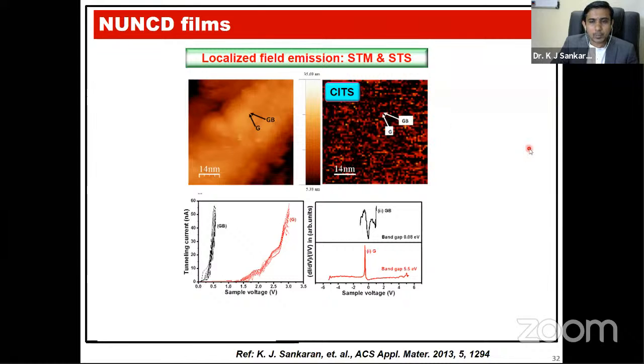So the red region represents the electrons emitting from that region, and the black region shows there is no emission. If you see the tunneling current for the supply voltage, you can see that the grain boundaries emitted electrons with a low supply voltage compared to the grains. Also, the grain boundary shows a band gap that is metallic in nature, but the grains show 5.5 eV, which represents that the grains are diamond in nature.